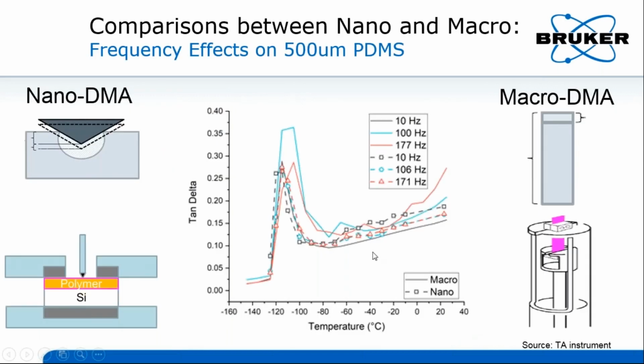Here we have the comparison of Tg measurements of a 500 micron thick PDMS, and the judgment rule is tan delta peak. We have two sets of DMA results at the same temperature range and the frequency level, but at different scales. One clear advantage shown here is the convenience of direct measurements for thin film samples. For this case, with the thickness of 500 micron, it is not that difficult to put the PDMS sample and fix it for the macro testing.